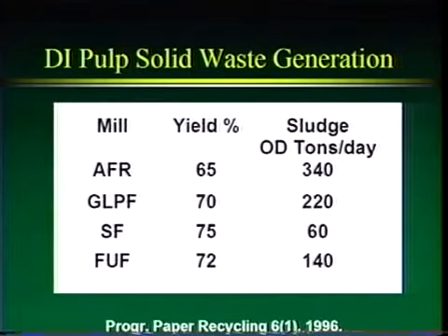So we're getting 25 to 35% waste. And then if you look at the amount of sludge in oven-dry tons per day, you can see that it is very, very high, 340 oven-dry tons per day. When we think about sludge, we need to realize that typical pressing can only get us to about 50% solids. So that 340 oven-dry tons per day really represents 680 wet tons of sludge per day. So you can see that basically that AFR mill was producing about 650 tons of product per day, and it was producing about 680 tons of wet sludge per day. So it's actually producing more sludge than it was product. Interesting thought.